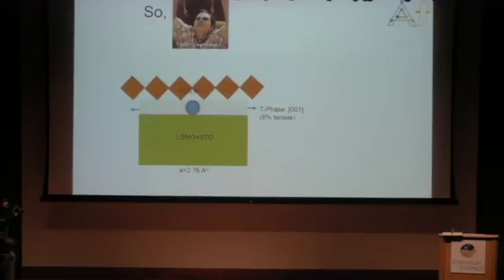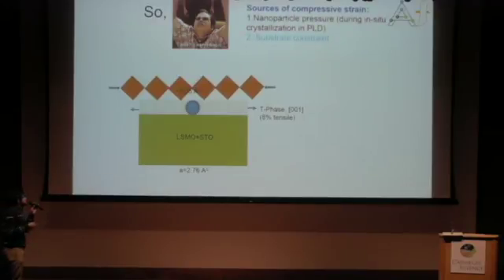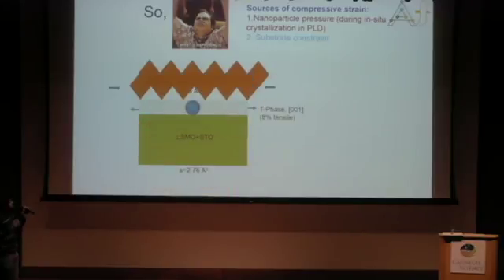And in fact, this is well known in the literature of zirconia. What happens in PLD, for instance, is there is in situ crystallization, so we have the formation of nanoparticles. That is one source of compression, or compressive stress. And then the second one is the substrate constraint. So using these two, we actually compress this cubic or tetragonal phase into a rhombohedral phase.